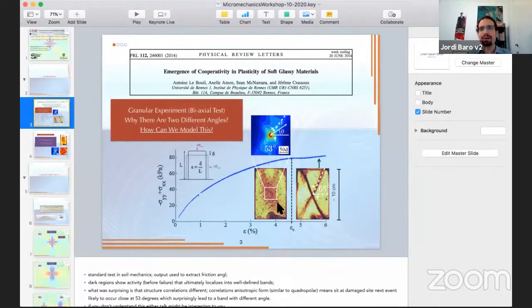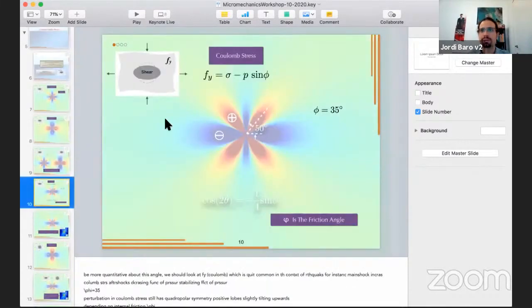Thanks, Kamran, for the talk. When you compare the frictionless with the frictional model, I was wondering if there is an equivalent of the frictional model when you consider Lennard-Jones potentials. When you are trying to model amorphous solids, it looks like everything will give place to creep, right? If you're talking about bulk metallic glass, for example, there's not really friction. It's more like a molecular glass. So you don't have friction at the atomic scale, unless you fracture the sample, and you might get stick-slip type behavior between the micro-fractured surfaces. But apart from that, I don't think this is directly comparable to those kinds of systems, I mean, a real solid.